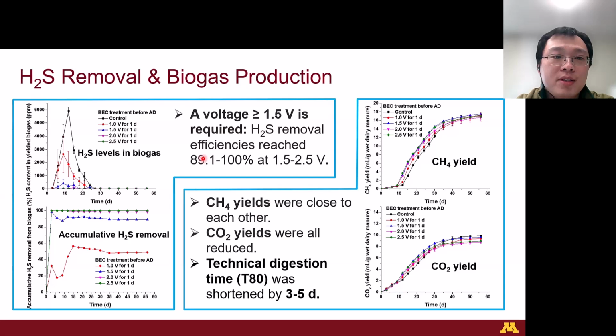And these are the hydrogen sulfide removal and biogas production results. We found that all bio-electrochemical groups showed hydrogen sulfide removal, but a voltage of over 1.5 volts is required to secure a high sulfide removal efficiency of over 89%. Meanwhile, the methane yields remain stable across all the treatments, while carbon dioxide emissions were slightly reduced, therefore improving the biogas quality.